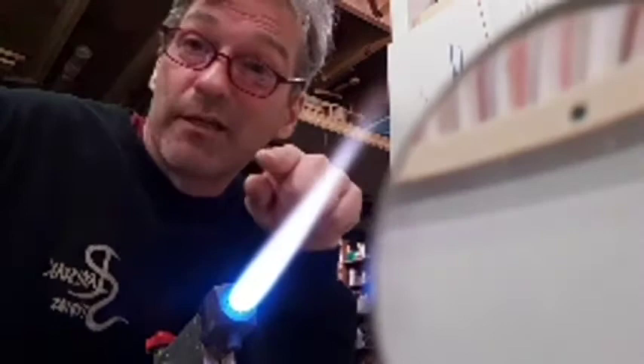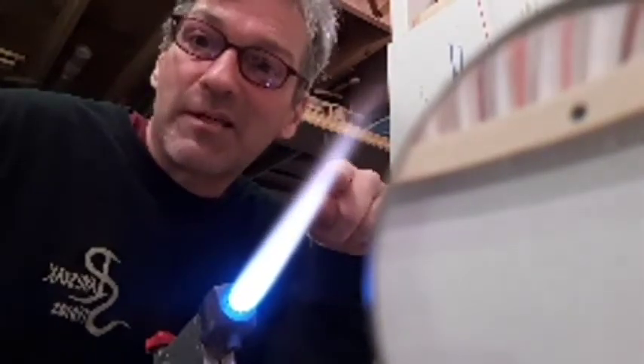I always try to make sure that last punty and last little glass rod is clean so I'm not leaving stuff attached to the glass surface. It looks like I did a pretty good job. I'm heating up a little tweezer to orange, then letting it go to black — down to about 950 — and I'll pick up my marble. It looks like a black flower on a black background right now, but once it hits room temperature that red art deco flower on a black background will really pop. I'll put it in the annealing oven — a smaller marble needs to stay in the annealer for at least an hour, then the temperature ramps down in 45-minute increments by thirds. Thanks for watching, I'll see you guys next week!